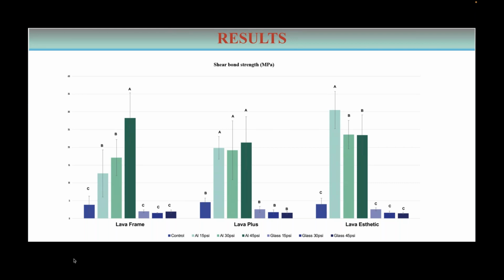So we can see the more the pressure, the higher the bond, and this is statistically significant for the 45 psi, which has the A letter, compared to the 15 and 30 psi, which have a B letter. For the Lava Plus, we have C as a control, and then we have the A letter for the three pressures. When we use the alumina, it's statistically significant compared to the control or the glass bead treated group.